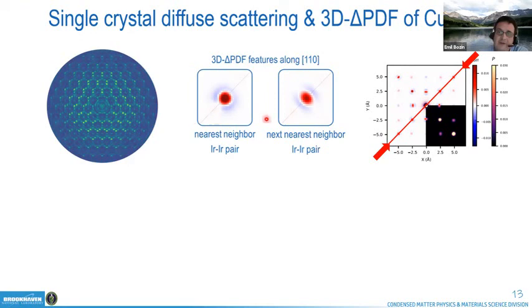And you see immediately that this signal is quite different for the two types of neighbors. In the case of next nearest neighbors, this signal is highly symmetric with these blue wedges and intensity in the middle, whereas the signal for the nearest neighbor is actually asymmetric, with some intensity appearing to be missing towards the origin of the direct space.